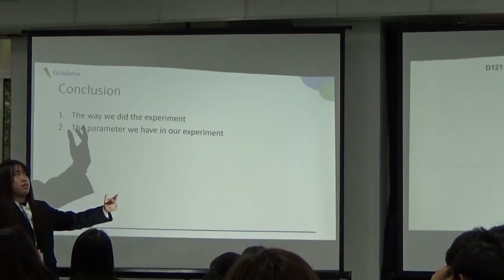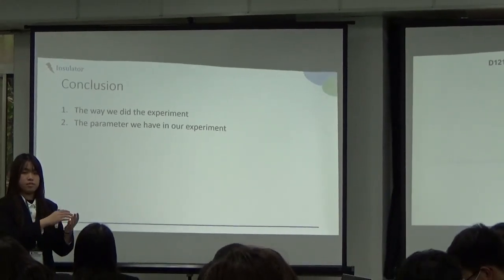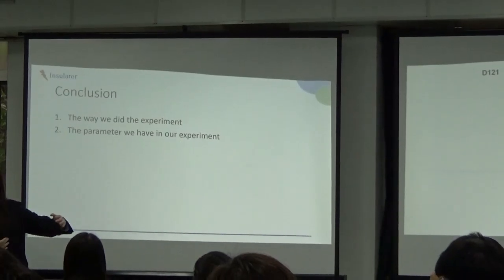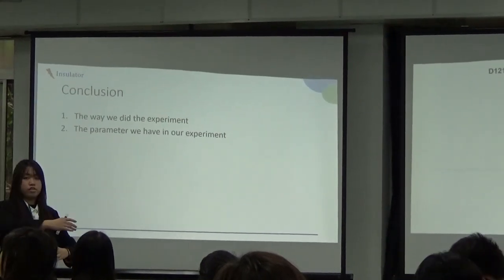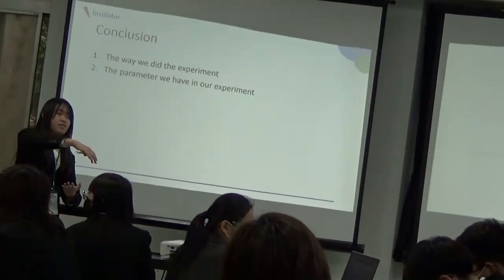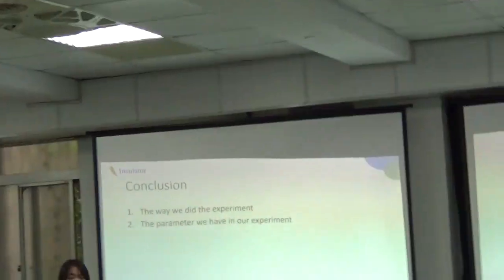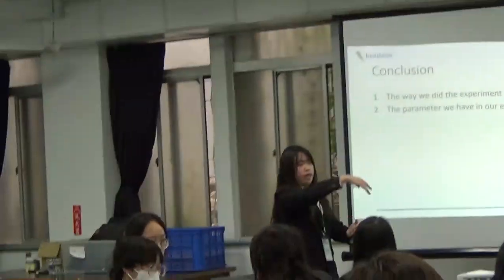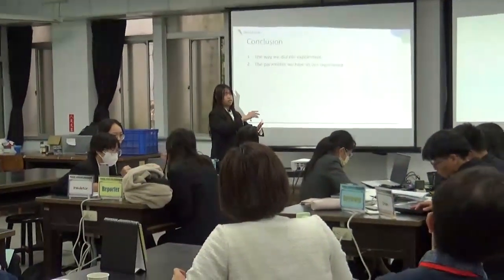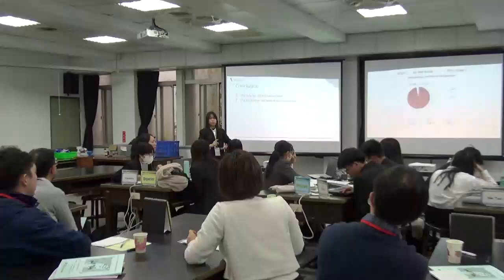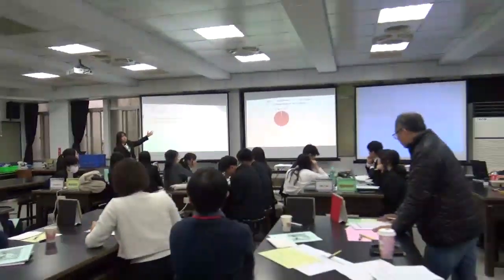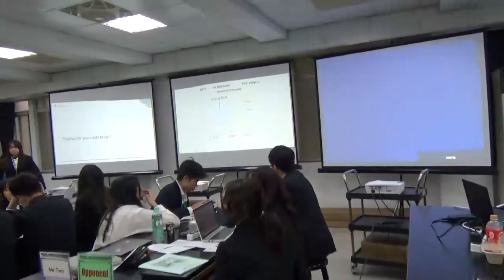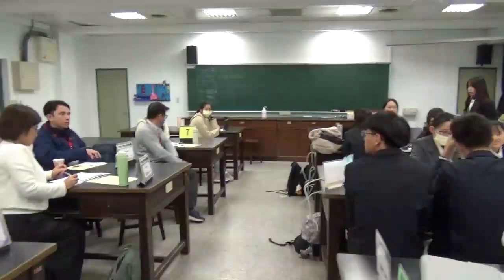And I also used the relative expansion of the different sides of the tracing paper and the Young's modulus calculation to explain the relationship between the curl direction and the fiber orientation. And we have done many experiments, like different aspect ratios and different areas of the tracing paper, to explain this phenomenon.